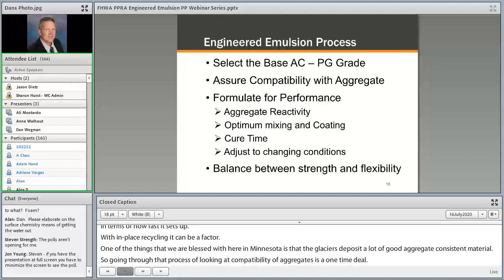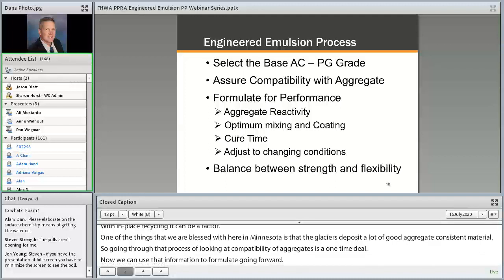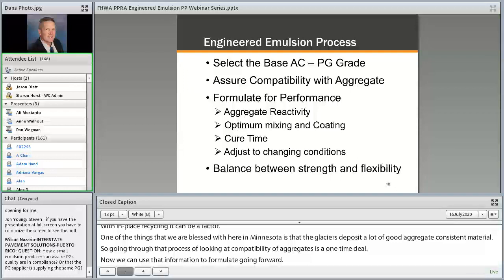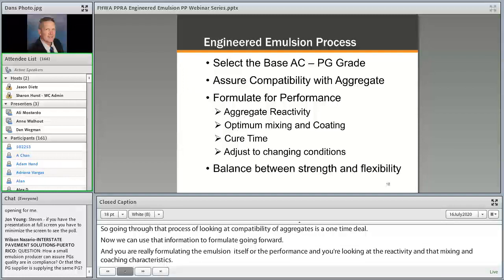And you're really formulating the emulsion itself for performance. You're looking at aggregate reactivity, the mixing and coating characteristics, and what kind of cure time you need. That is both for having the material set up and be able to handle traffic, and also to be able to get the material placed and constructed properly before it does set up. So both of those come into play in terms of a successful project.